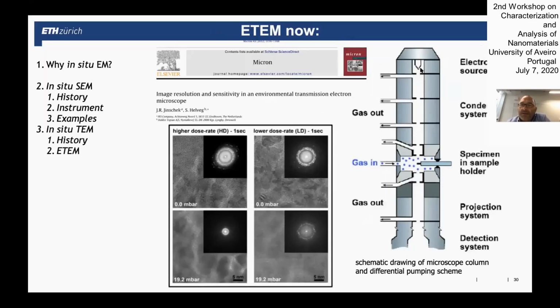Similar to the SEM, and similar to what Ruska did, you have a place where you create the beam, you have some lenses to condense the beam or to control the illumination. And then at one point you have the sample. Similar to the other instrument, the SEM, you make sure that the beam can travel nicely through vacuum, and only close to the sample there's a region where the gas is present. You do this by differential pumping apertures. And also in this paper, a modern version of what Ruska did, you can see studies on how, depending on the pressure of the gas, you lose resolution.